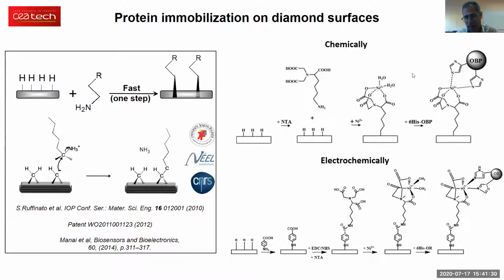And as Krishna and Carla described before, OBPs and MUPs, for instance, have a binding site which is localized on the protein, and it is crucial that this binding site is actually facing up, so it can actually bind with the ligand. So this is a very efficient way to immobilize this protein on diamond surfaces. We can also use some electrochemical approaches if we have a boron-doped diamond.